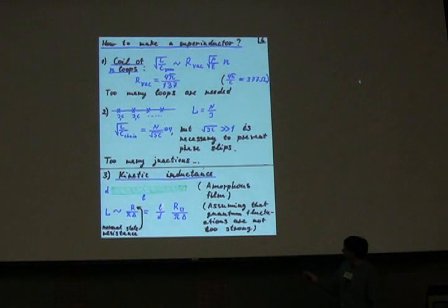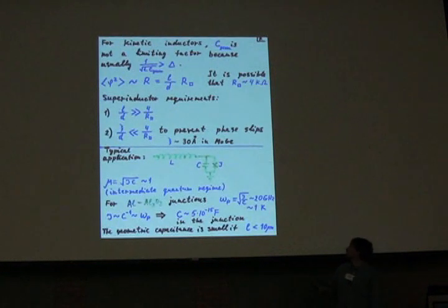Basically we need two things. We need that the resistance per square of this wire is large enough, and that the aspect ratio is large too. The resistance per square cannot be very large. It's limited by the same quantum unit. The maximum value one can have is about 4 kilo ohms. However, the aspect ratio can be arbitrarily large, and it's easy to achieve that the aspect ratio is much greater than this number,